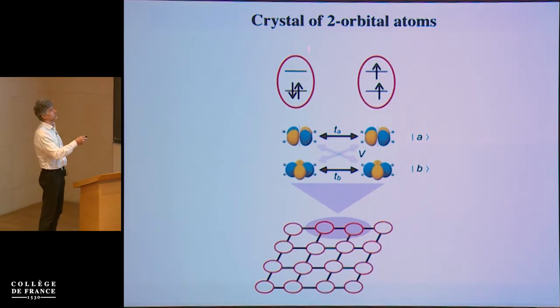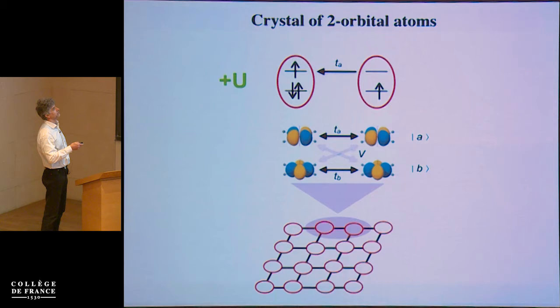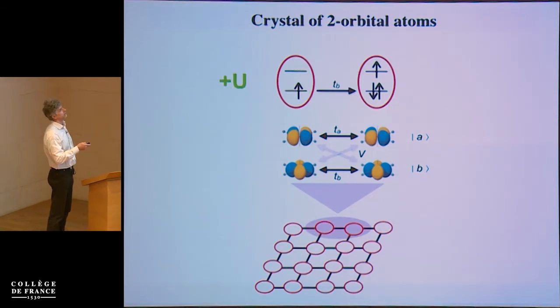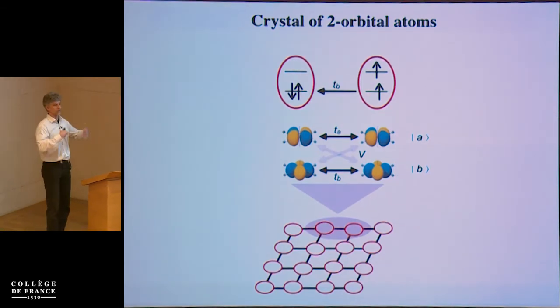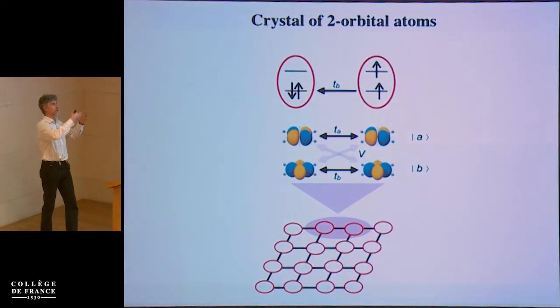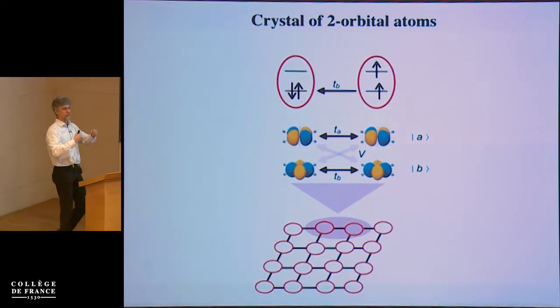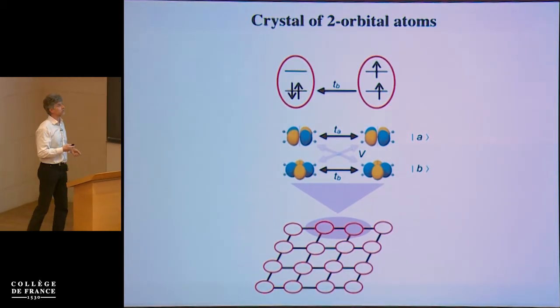We can start with 1 atom in the low spin and 1 atom in the high spin state, and we can have such an excursion back and forth, or an excursion in the lower band, which would of course reduce the energy of the high spin low spin dimer with respect to 2 isolated atoms.